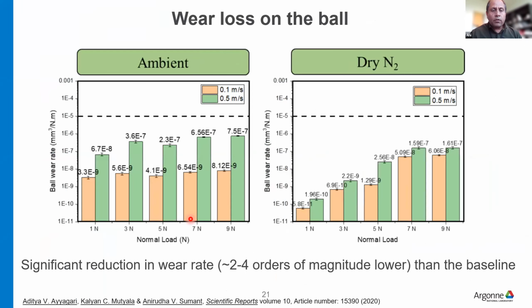And then when we calculate the wear, and this is the benchmark, we look at the reduction in the wear, in the ambient and also in dry nitrogen, about 2 to 4 orders of magnitude lower than the baseline, which is excellent.